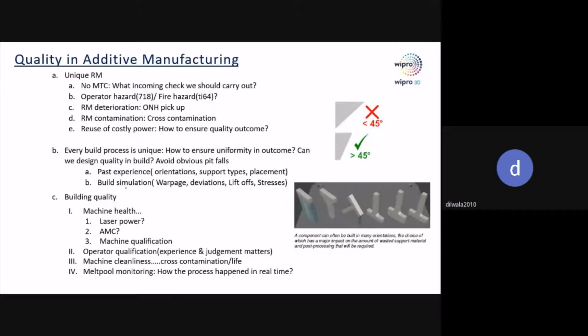Then comes operator qualification. This becomes very important as there are judgments that he has to make. Is the build plate properly loaded? Is it properly dialed? Is the powder spread adequate? Is it uniformly spread throughout the build plate? Is the recoater properly cleaned? Otherwise this might lead to line marks on the actual part when the recoater is moving along the build plate. Then ensure no particulates are present on the build chamber walls.